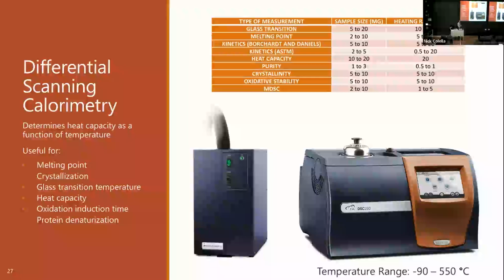We can look at crystallization and melting via the DSC. The limitations on this, we can only go up to 550 degrees, so most organic materials are going to degrade well before that, and we can cool down to -90. So if you have something that's liquid at room temperature, we can look at how it crystallizes, exactly what is the crystallization point, and then heating back up, what's the melting temperature.